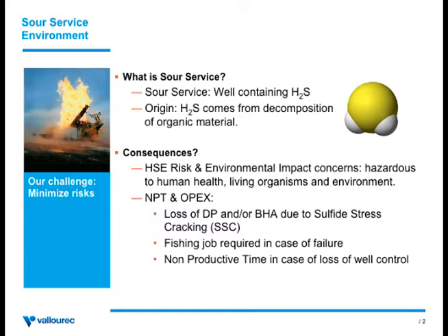H2S actually also interacts with steel. Any kind of steel tubular can be affected by H2S through a phenomenon called sulfide stress cracking, which I'm going to refer to as SSC to make it shorter. Basically, that failure can lead to the loss of the whole drill string, the BHA, but can also have consequences on the casing and tubing material. Of course, consequences of such failures would involve fishing jobs, large OPEX, and non-productive time. I've seen cases myself where it took more than 40 days to retrieve the BHA and to regain control of the well.